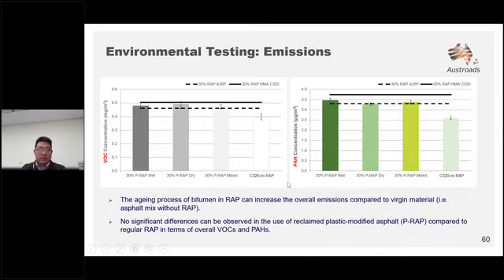So in terms of the emission test, the aging process of bitumen in RAP can increase the overall emission compared to the virgin material, as we can see from the results for VOCs and PAH here. So that is the result of the fresh asphalt mix, and these are results of the asphalt mix with 30% of PRAP and RAP. And similarly in the case of PAH results. No significant differences can be observed in the use of reclaimed plastic-modified asphalt, P-RAP, compared to regular RAP in terms of overall VOC and PAH.